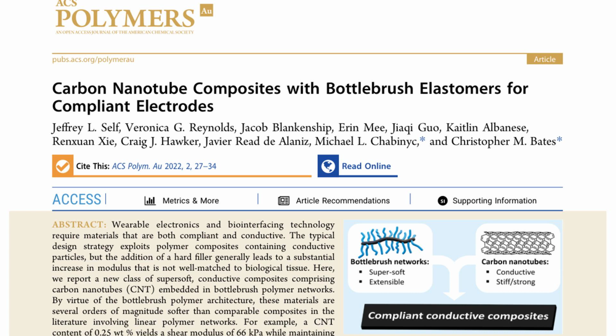The CNTs were chosen as the conductive filler due to their flexibility and high aspect ratio, which enable percolation at lower loadings than spherical particles. The addition of CNTs resulted in composites with shear moduli ranging from 66 to 140 kPa, which are significantly softer than composites containing linear polymers. The conductivity of the composites was in the range of 10⁻² to 10⁻¹ S per meter.